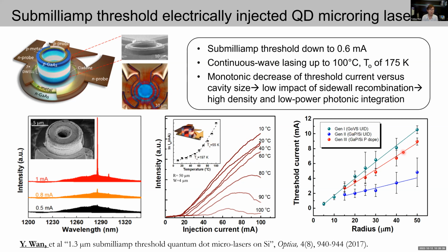More importantly, we can take a close look at this figure, which shows how the threshold current changes with a reduced cavity radius. We can see that even at the smallest dimension, which is set by the limit of our lithography tools, the threshold current is still showing a monotonic decrease with the radius, which indicates a very low impact of sidewall recombination. So this kind of downscaling capability, these compact geometries, and the low power consumption are very promising for high density and low power photonic integration.